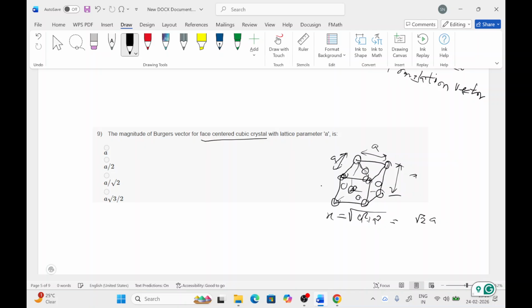But the distance we have to travel is only half. So the magnitude of the Burgers vector will be x by 2, which is root 2 a by 2. So this will give a by root 2. So the correct option for this is C, a by root 2. Similarly, we can find the Burgers vector for the BCC and simple cubic also.